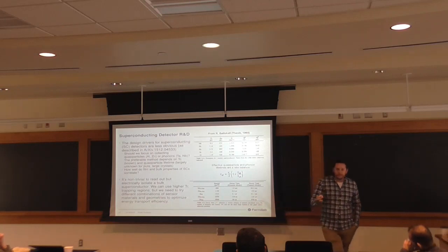And you can quantify this. You can quantify all of the different carrier lifetimes in these materials. There are different trade-offs. Between niobium, aluminum, and titanium, lead, they have different TCs. They have different binding energies, and they have different phonon spectra, right? So the TC is determined by the quasi-particle phonon dynamics to a certain extent. And you can use these either as quasi-particle readout devices or phonon readout devices.